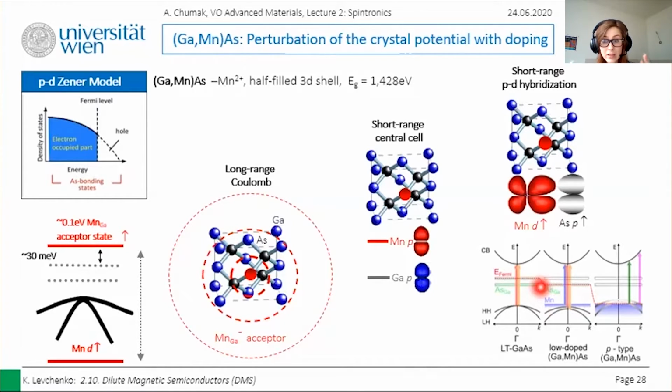So we have delocalized holes with a low temperature density, and the manganese density is two orders of magnitude larger in this case than in gallium arsenide with shallow acceptors. So the long-range Coulomb potentials are screened, and we arrive at an imperfect metal with disorder-broadened and shifted bands.